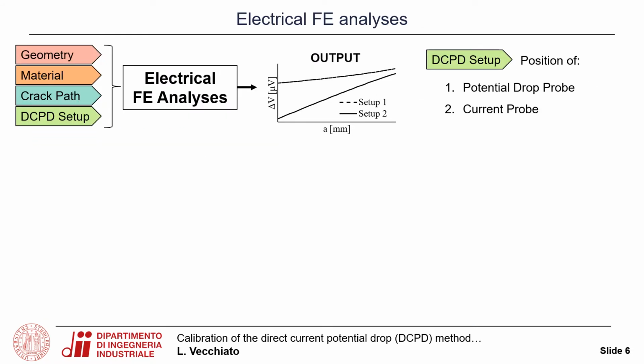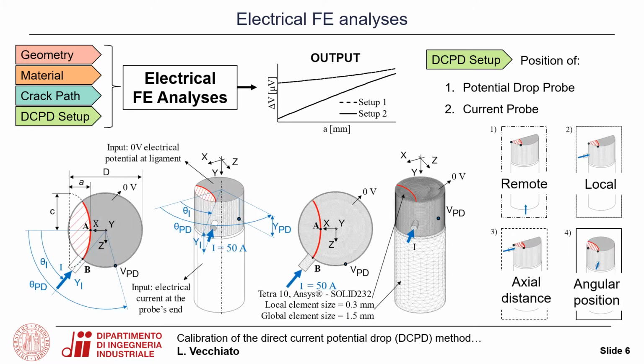The last parameter to be analyzed was the DCPD setup, so the position of both the current and the potential drop probe. For doing this, the finite element models have been realized according to the reported images, so taking advantage of the ZX symmetry plane, half of the specimen was realized. The current was injected in four different manners.